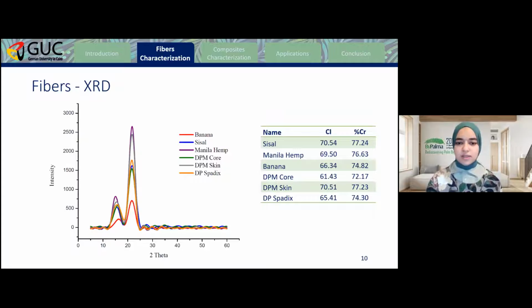As for the results of the XRD, the crystallinity index and percent crystallinity in the 6 types of fibers were calculated, and it was found that sisal and midrib skin fibers had the highest crystallinity index and hence the highest percent crystallinity, followed by the manila hemp, banana, and spadix stem fibers. The crystallinity index indicates the amount of cellulose present in the material, and as the crystallinity index increases, it indicates dominance of the cellulose element, which is the load-bearing element, and hence gives insight on the mechanical properties of the fibers.